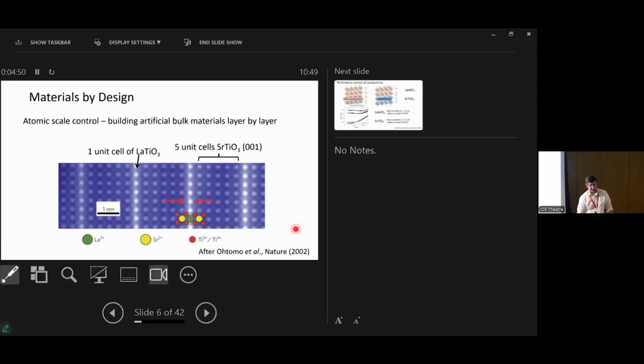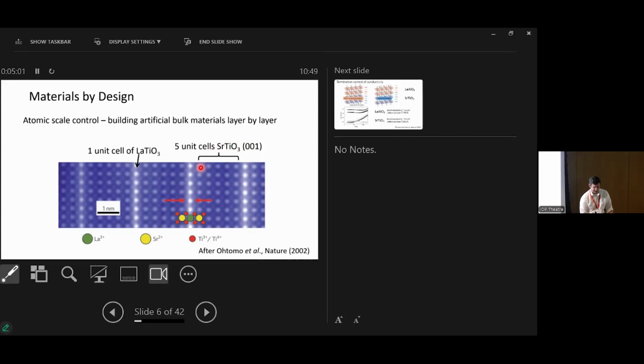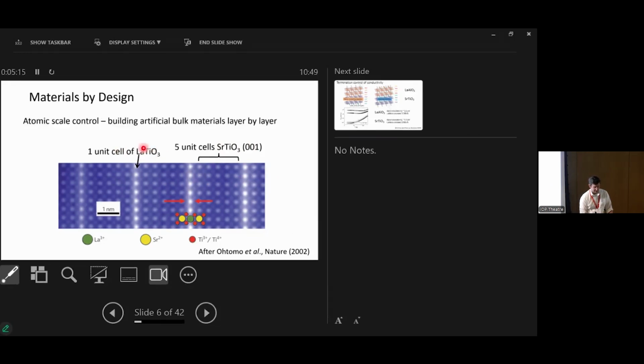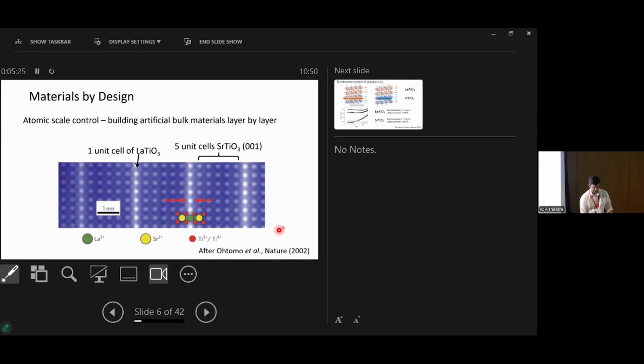There are many ways to do it, different thin film growth techniques. I'm not going to go into them. This particular image is a transmission electron microscope image of strontium titanate, this material here. These 5 dots represent a row of probably 100 atoms into the page, but this is atomically resolved imaging. And then this brighter row is one crystal unit cell of lanthanum titanate. So again, you're just changing one chemical element, lanthanum, to strontium. So you can build up these artificial materials in a layer by layer way. And this was done by Harold Hwang and his collaborator Akira Ohtomo 20 years ago now.